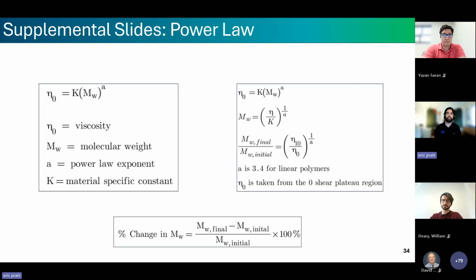Now, typically, you would need a material constant to determine molecular weight from viscosity. But since we were looking at a change rather than an absolute value, we can negate the material constant and report a change in molecular weight. To do this, we use the power law with some equations shown here on the slide.